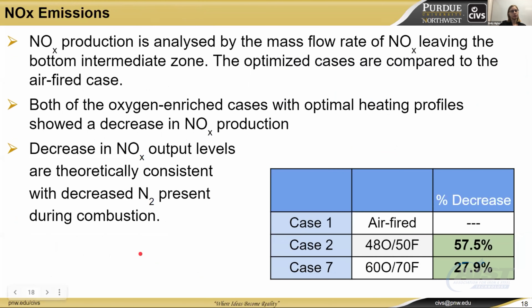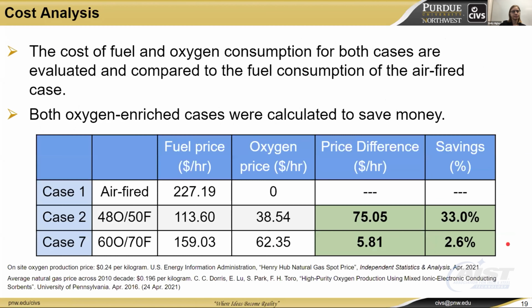So for NOx emission, the main thing to note here is that for oxygen, a larger percentage of oxygen is included in the oxidant relative to nitrogen, which means that there is less potential for NOx to be produced simply because there is less nitrogen. And as we can see, based on our simulations, less NOx was produced in both cases 2 and 7, with the greater decrease occurring for the lower enrichment level.